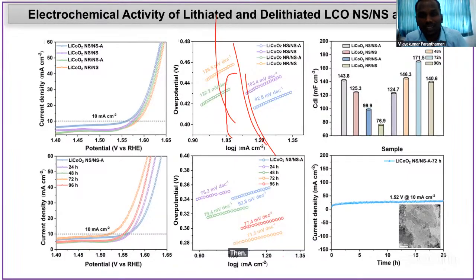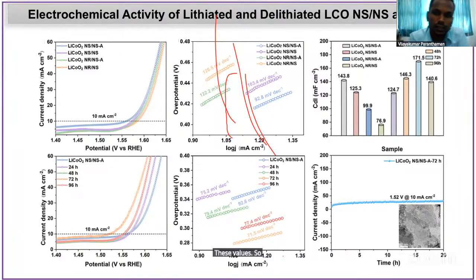Then the electrochemical double layer capacitance. A higher double layer capacitance confirms a higher specific surface area. Using the double layer capacitance, we can calculate the electrochemical active surface area, ECSA. We can calculate it from these values. After the delithiation, we used the bare material, then 24 hours to 96 hours, and the 72 hour material performed better. Approximately 280 millivolt overpotential has been obtained. It resembles our Tafel slope, with good reaction kinetics of around 71.5 millivolt per decade.